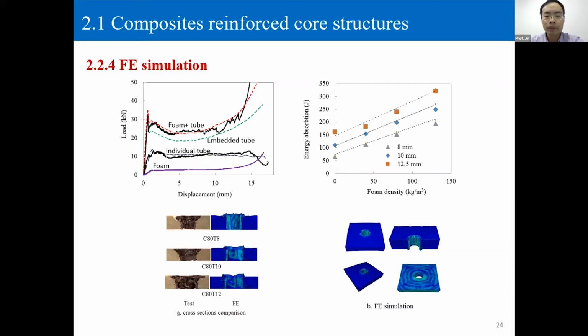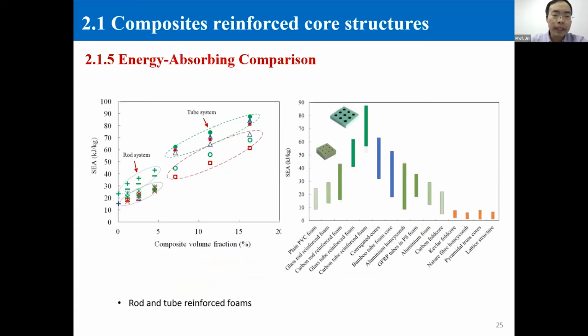For the composite tube reinforced foam, we get this chart. The figure on the right shows the energy absorption of those structures with different composite tube diameters. And the figure on the left-hand side shows the dynamic loading rate on the two different structures, the rod system and the composite tube reinforced system. We found that the energy absorption capacity of the rod reinforced foam increased compared to loading at a quasi-static rate, while the energy absorption of the tube reinforced foam was reduced compared to quasi-static.